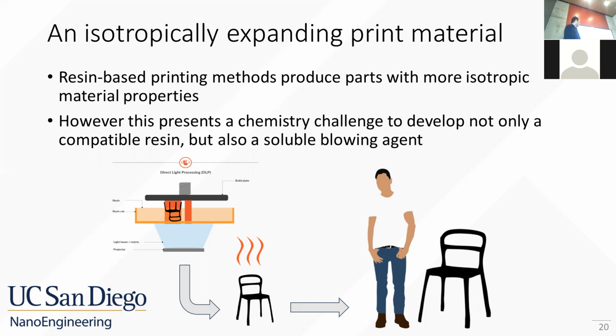However, this presents a chemistry challenge. Developing an SLA or masked SLA print resin is a lot more challenging than just incorporating a blowing agent into an FDM filament. This is because in a filament, you can have a relatively homogeneous mixture of blowing agent and polymer, because it's solidified in place once the polymer is hardened into a filament. With a resin, if this blowing agent isn't fully soluble, it'll settle out during the course of long prints.